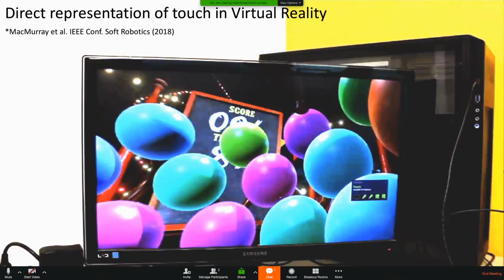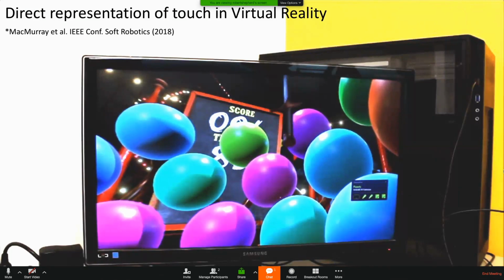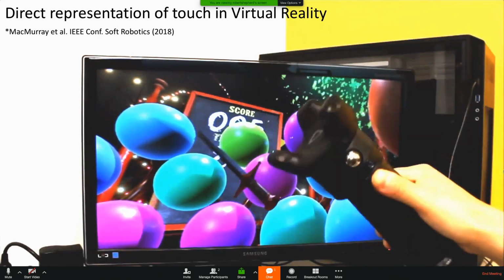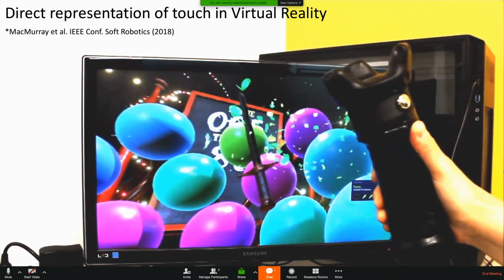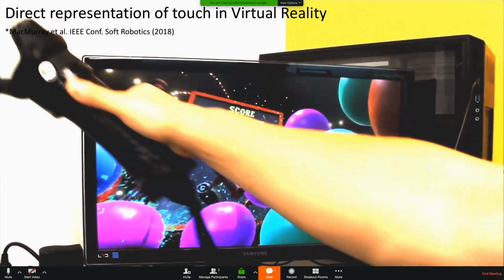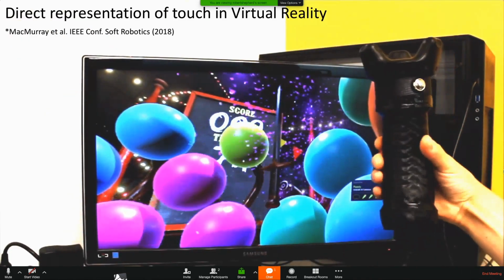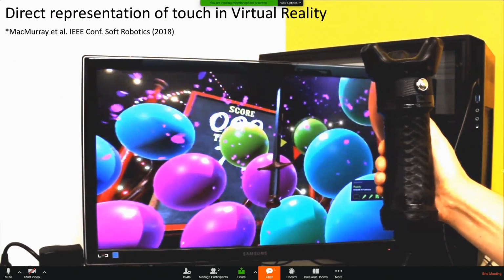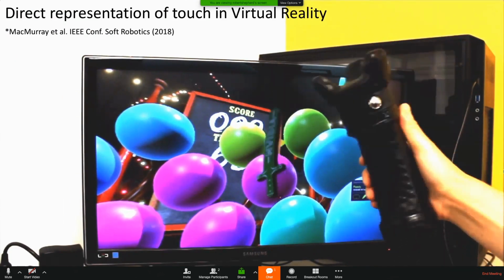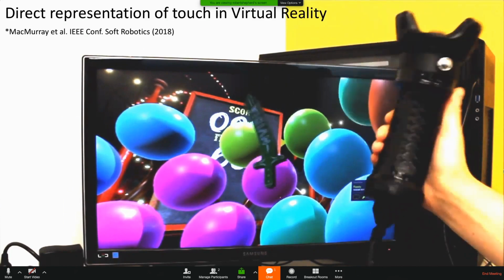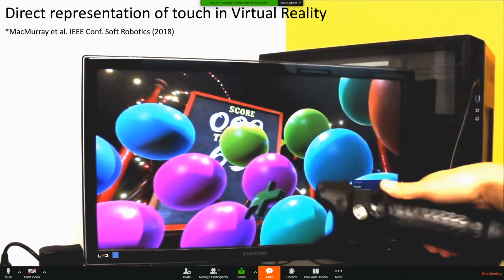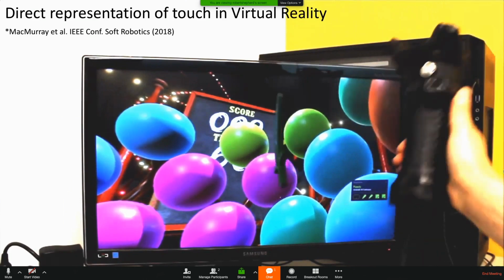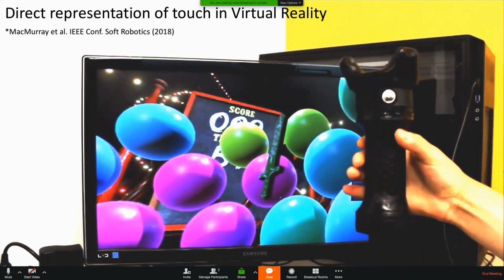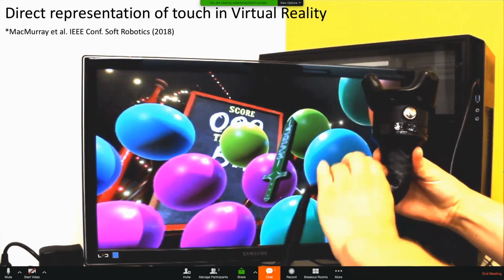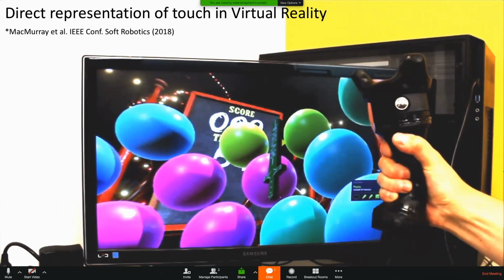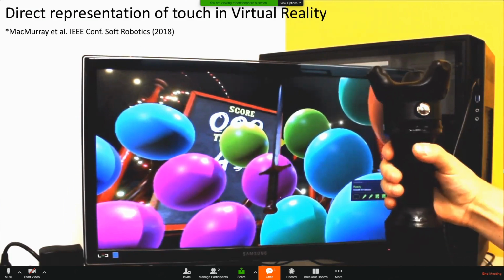So using 3D printing, we do like haptic interactions as a way to demonstrate the value of it. We printed, this is using the Carbon M1's elastomeric polyurethane, a handle that we could stiffen. It's got a lot of internal lattice work that allows it to keep its shape when it's inflating, but still be stiff. Then what Ben just did there is he squeezed on the handle to send a barometric trigger that started deflating the handle, and then he pressed that metal button, which changed the sword from a steel sword into a foam sword. And when it's in this configuration, you can't pop balloons, and it feels just like foam. So unlike the abstract representation of haptics before, this is a direct representation of it.